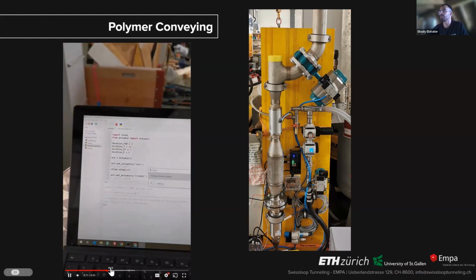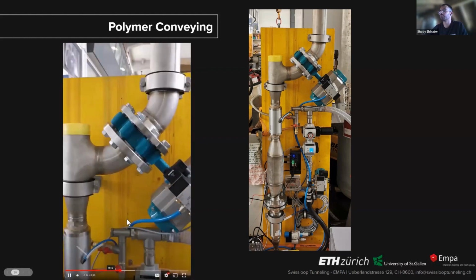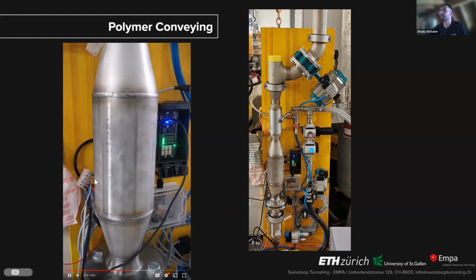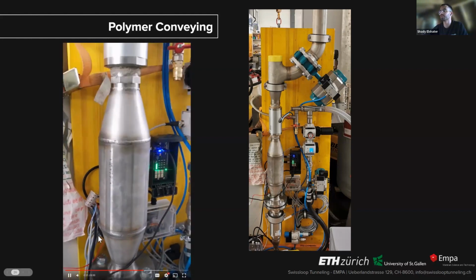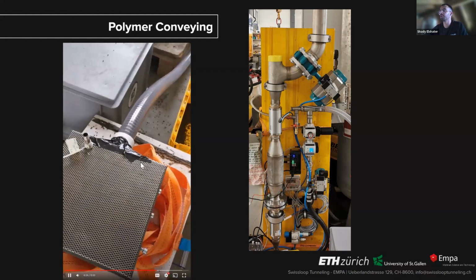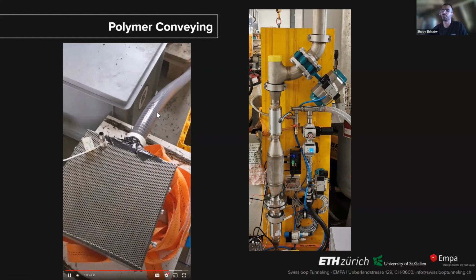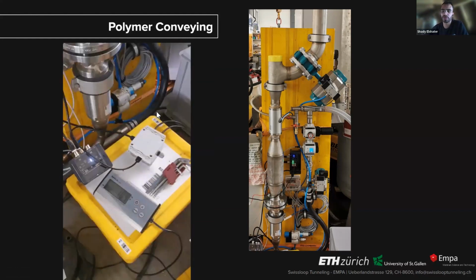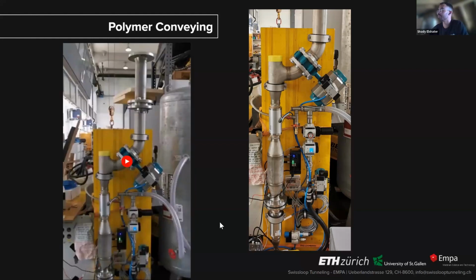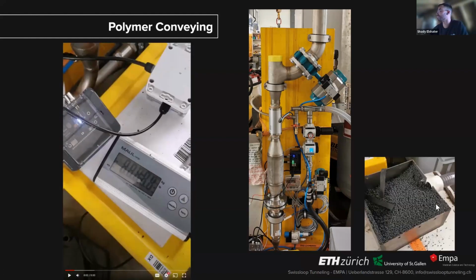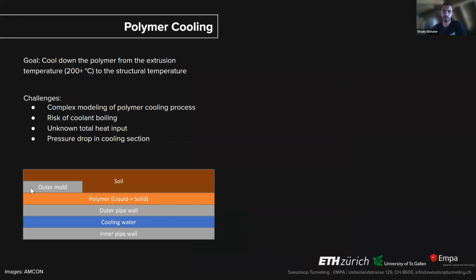This was just a simple code which we start, a series of valves open. We fill a certain quantity inside, and then we start the conveying. Here you can see the tubes where there are particles flying at around 70 kilometers per hour, which then go inside the hopper that we saw, which then looks something like this. Here it was an overfill test, where we pushed the polymer inside this small box, and we tested this system quite a lot. And it worked relatively reliably.